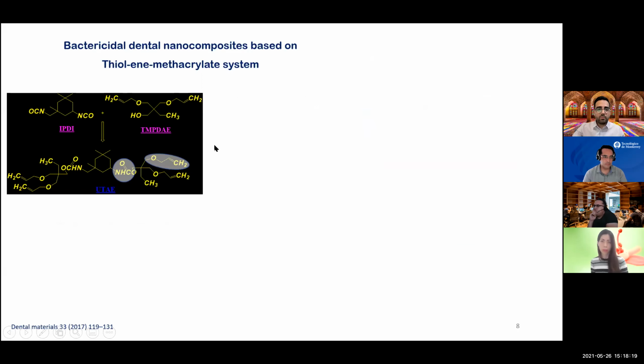So because we wanted to remove these problems, first of all, we tried to synthesize new monomers. We use diisocyanate monomers, and monohydroxyl group monomers that contain two different allyl ethers as photopolymerizable functional groups, and we synthesized these monomers. These monomers have 1, 2, 3, and 4 allyl groups that can undergo photopolymerization. As well, they have two urethane bonds, and this urethane linkage is really nice because it can help with better adhesion to the dental structure, and they have hydrogen bonds.